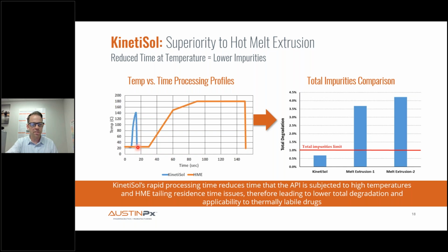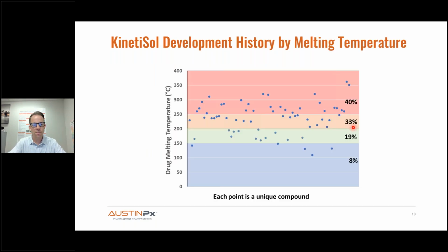And this is the temperature profile of kinetisol. So you don't need to do the math. You can look and see the area under these two curves is dramatically different. And what that equates to is substantial reduction in the generation of impurities. So compounds that are too thermally unstable for melt extrusion are perfectly processable by kinetisol, and that's the first advantage. A lot of companies would prefer thermal processing over solvent processing, but the issue is, as many of you know, melt extrusion is only applicable to, in my experience, about 20% of molecules. The rest are too unstable. And that's before you even get into excipient instability and high viscosity that limits the design space of melt extrusion. And so producing ASDs with a minimal amount of thermal exposure is one obvious and primary advantage.